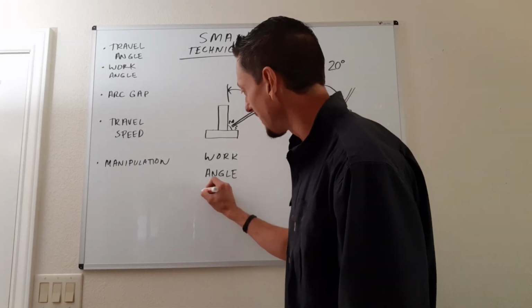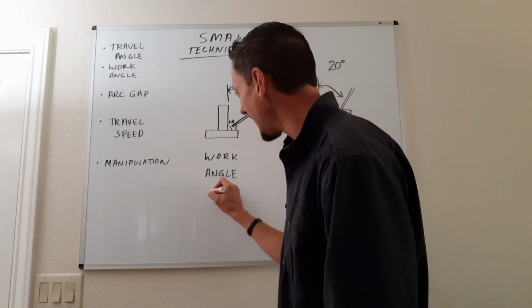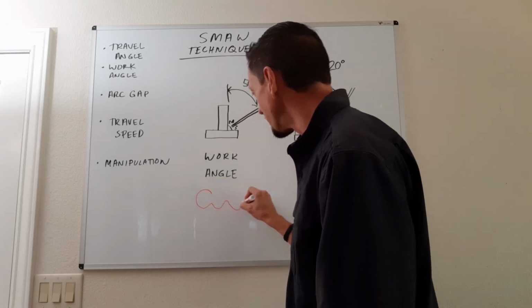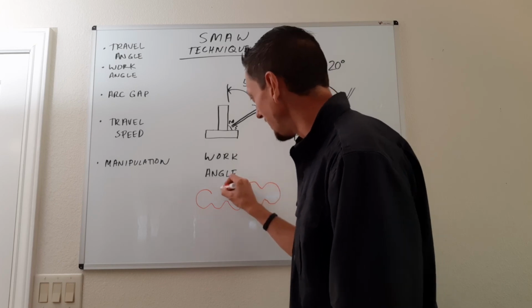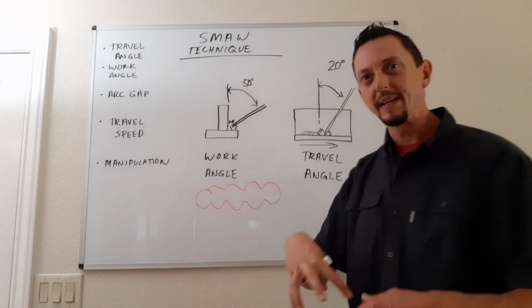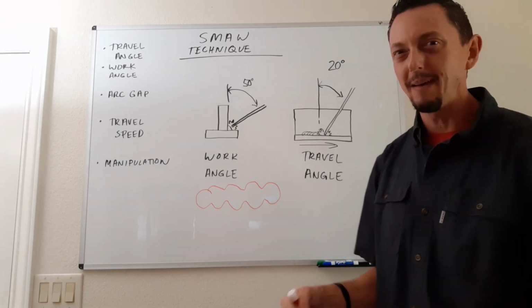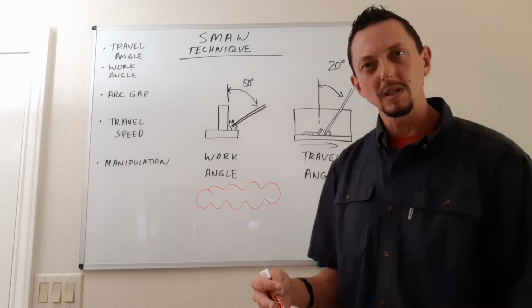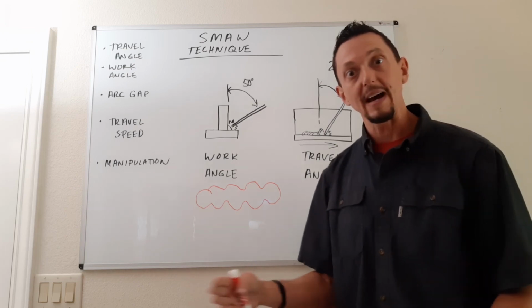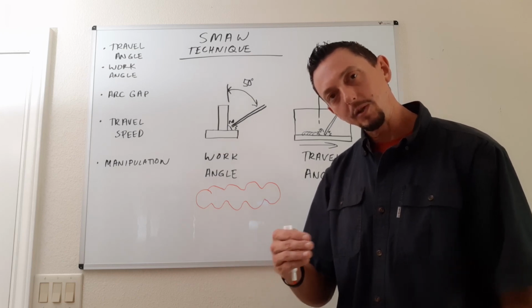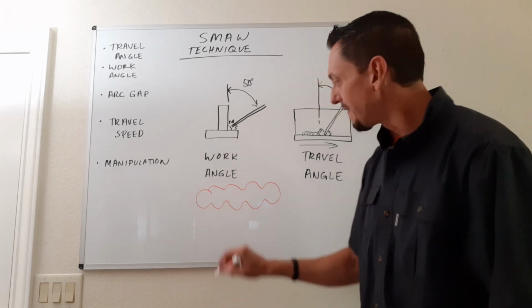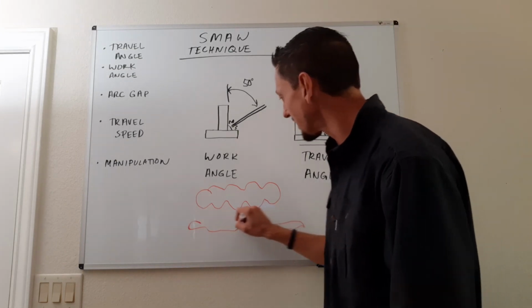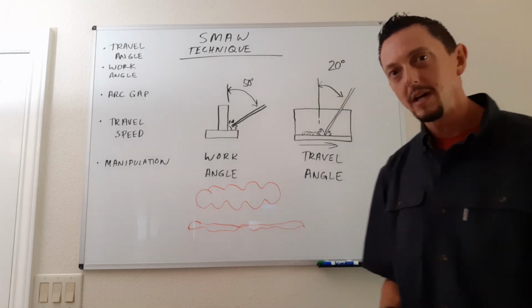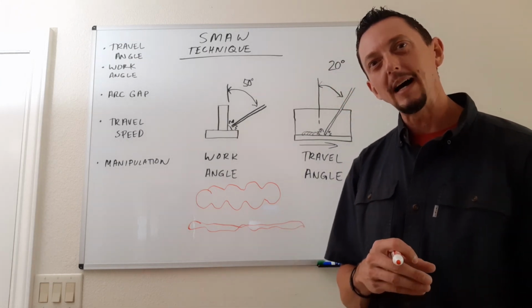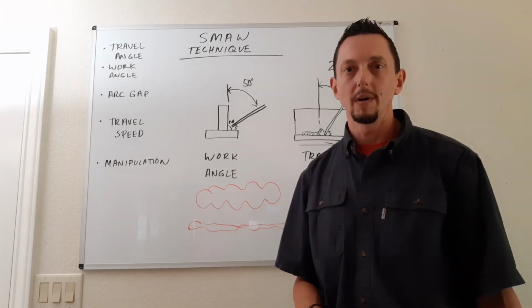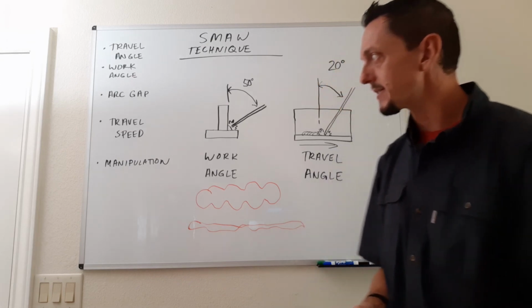Just for instance, if your weld profile, if you're looking at it from the top and it's a very, very large kind of just piled up weld that's real big and wide, then okay, maybe my travel speed is a little too slow, or maybe it's not consistent. I'm going fast and slow and fast and slow, so I need to try to maybe speed up just a little bit but keep it consistent. If it's very, very thin and just kind of irregular and just kind of sitting on the surface, then okay, maybe I'm going a little too fast. I need to let that fill up and then try to maintain that speed as I go forward. Okay? Travel speed, very important to the appearance of a weld.